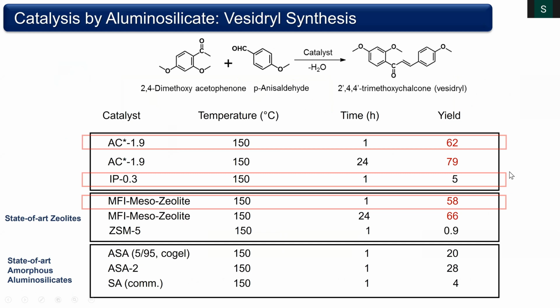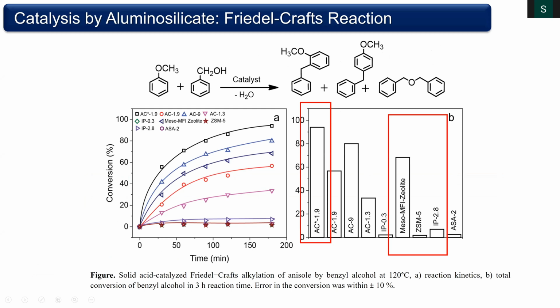And we showed a range of different reactions like this particular catalytic reaction. You can see ZSM5, the zeolite, is one of the best solid acids, but it doesn't convert because it has very small pores, whereas ours gives a 62% yield. Another zeolite reported in the literature was a mesoporous zeolite. So ours is very close or even better than the mesoporous zeolite. We tried different other reactions to show how good our catalyst is in terms of acidity and kinetics. Acidity because of the zeolitic type acidic site, and kinetics because of the porosity of the material.